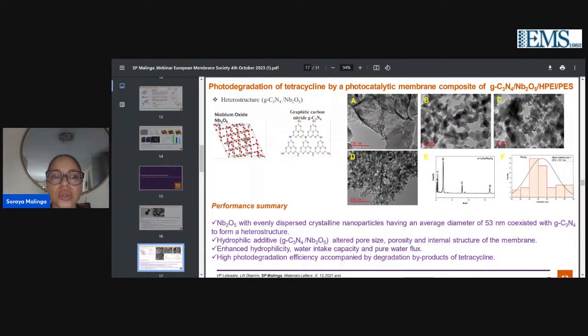In our latest work, we also targeted another pharmaceutical. We looked at tetracycline and a heterostructure in this case, where we looked at graphitic carbon nitride and niobium oxide. Because we first prepared the niobium oxide on its own using HPEI as the dispersant or the host, we found that we could get very small diameter nanoparticles that coexisted with the support, which was graphitic carbon nitride in this part. Graphitic carbon nitride is very useful as a nanofiller because it has its own photocatalytic activity.